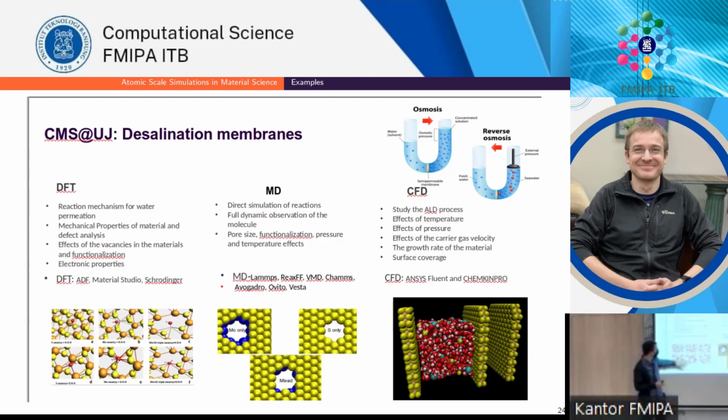So for example, you would ask here, what is the surface interaction of the water and the MoS2? What is the interaction of the water with certain kinds of defects, right? Obviously, in the MD we are working with defects of a larger size, like 5, 6, 7, 8 atoms. But with density functional theory, you can create a smaller defect. And basically what you need is a reactive site, right? It doesn't really matter whether you have 20 atoms missing or 3 atoms missing, you want a reactive site.